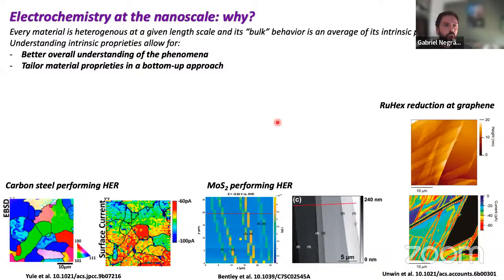And it's real as well for electrochemistry. Here I'm just taking a few examples from papers using those techniques we're going to discuss, just showing that those techniques are able to map chemical or electrochemical properties and show that they are quite different and quite heterogeneous. So here, for instance, carbon steel, and we're looking at the hydrogen evolution reaction, which some studies tie to corrosion. This is a map of the crystallographic orientation of that surface, and this is the same map of the current of the hydrogen evolution reaction, showing that different areas perform that reaction very differently, and there's a correlation with the crystallographic orientation.